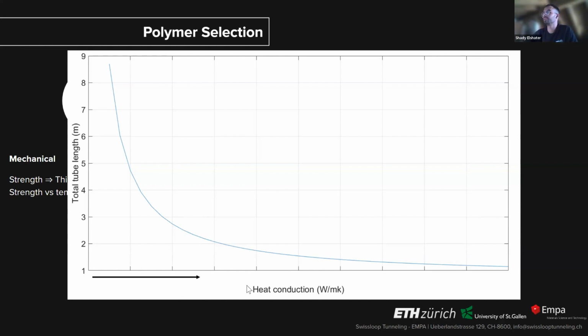And you can really see that the heat conduction of the polymer as a property can have a big effect on the surface that you need to cool it down. So this total tube length is the length of the cooling section that you need to bring it down from the extrusion temperature, so more than 200 degrees, down to the structural temperature. And most of the polymers have a pretty bad heat conductivity. So most of the polymers really move in this area, which means if you don't find the right polymer, you're looking at a very long length to cool it down.